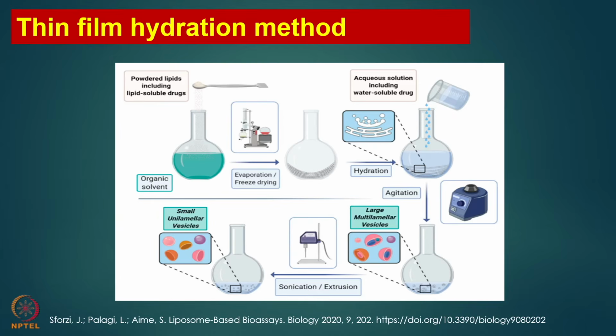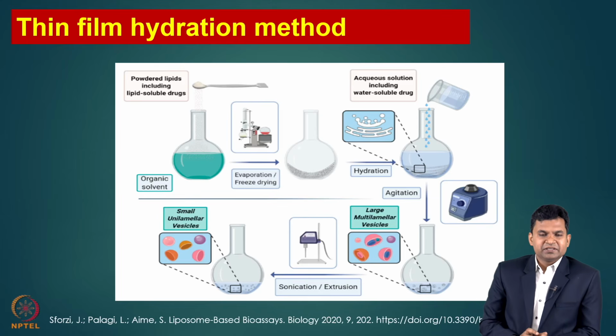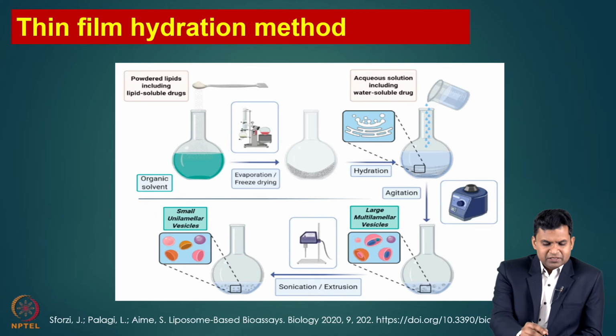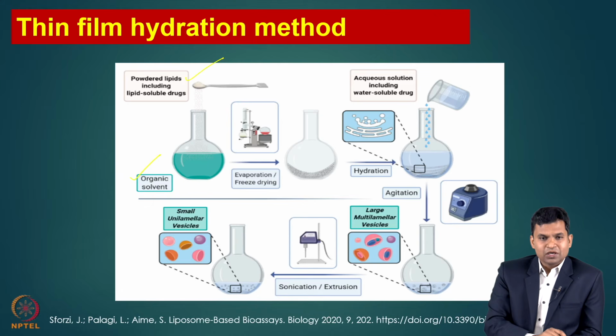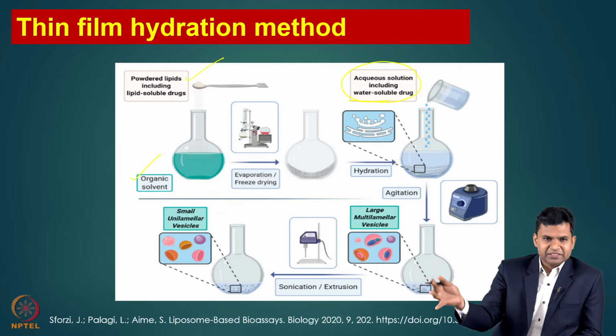Now, in the thin film hydration method, with this you will understand the general preparation method of liposomes. In an organic solvent, you need to dissolve your lipid first. If a drug is water soluble, you dissolve it in your aqueous solution in the second step, during the hydration.